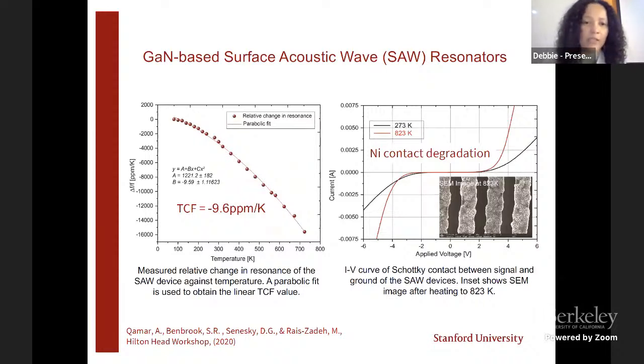And then just looking at temperature coefficient of frequency, as you expect due to softening, it does shift. And then also our nickel contacts, we observed degradation. These were not highly optimized contacts at the time.